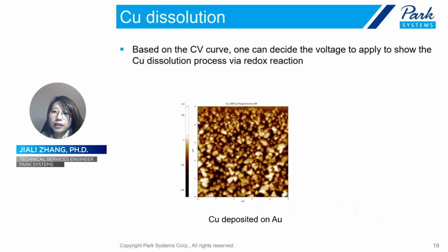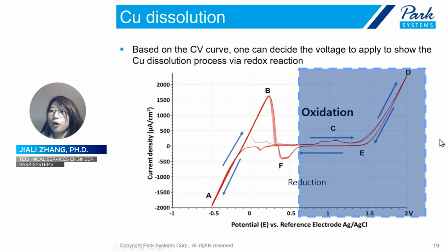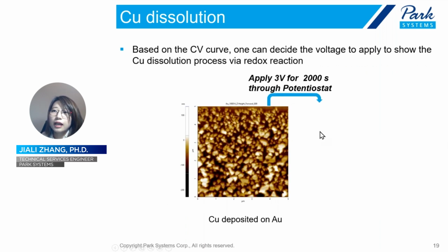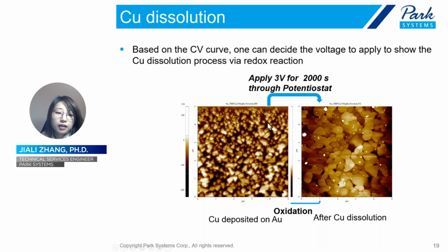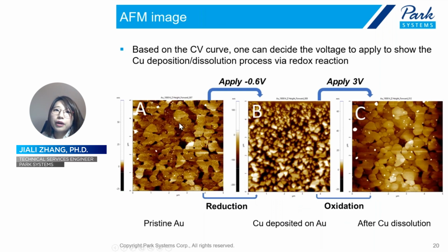Using the same imaging as an example and going back to the CV curve, if we choose to apply a more positive potential, like in here, by applying 3 volts, and then after that taking the image of the same area, we'll see that the deposited copper clusters were completely removed, and the bare gold surface is exposed again. By comparing these 3 images together, you can see that the gold domain remained the same by comparing A and C. You can see the hole here, and these domain features are exactly the same. So that tells us the reaction is fully reversible.